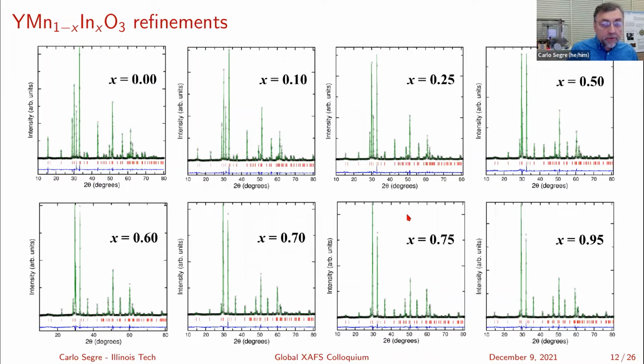We made the same samples, and we just made them by solid state methods, grinding and firing. And these are the samples we made all the way from 0 to 0.95 for x. And as you can see, 0 is full manganese, and 0.95 is just a little bit of manganese. This is the one that has the color to it. And you can see the Rietveld refinements here are quite good. So there's really no secondary phase. These are all refining to very good values.